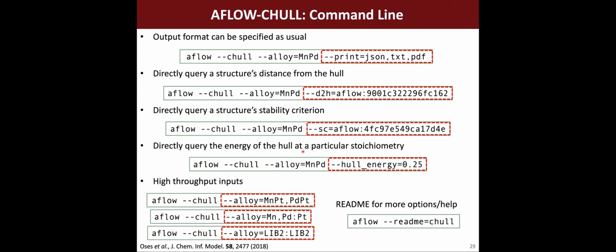Remember that the minimum energy surface, the minimum Gibbs free convex polytope, is defined as the union of all of these different n-1 dimensional facets, all these triangles or all these tie lines. So if I want to know what the energy is at any given point in that composition range, I can linearly interpolate and figure out the energy of the convex hull at that point, by feeding in the energy of the hull and providing the stoichiometry where you want to find out the composition.